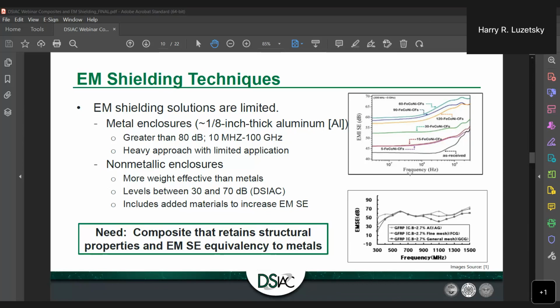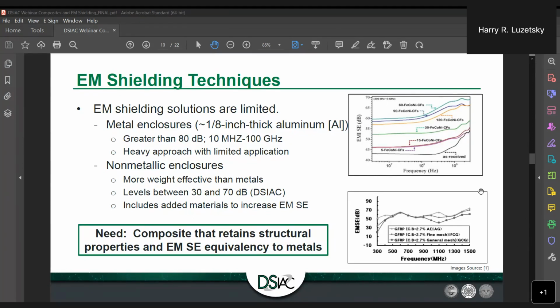As a note, there is an aircraft platform out there that once it was fabricated, if you will, it's even lower than that. We typically saw 30 to 50 dB in the electromagnetic shielding associated with the structure. So it gets a little bit sporty or tricky, however you want to put it, in order to actually develop your shielding that will appropriately shield your electronics in a given platform. Next.